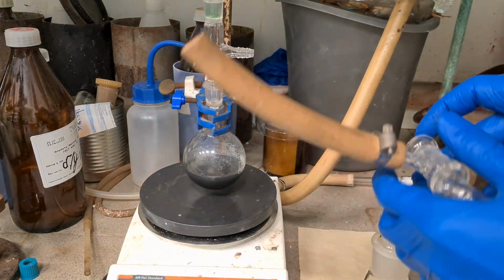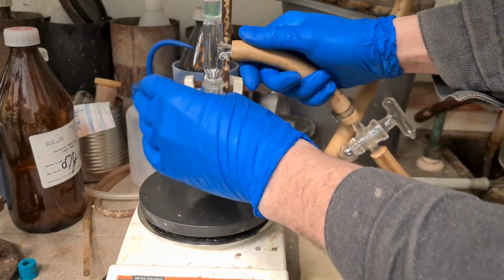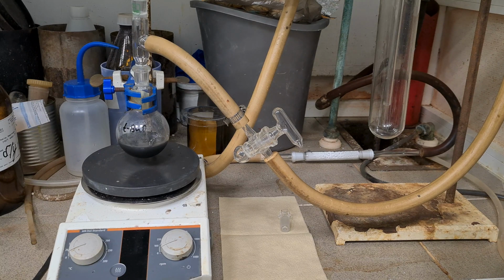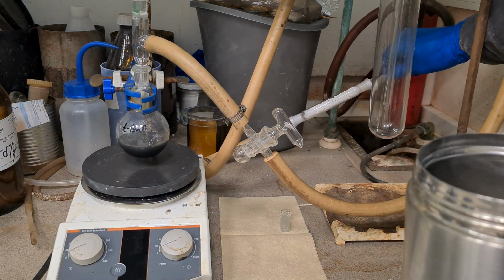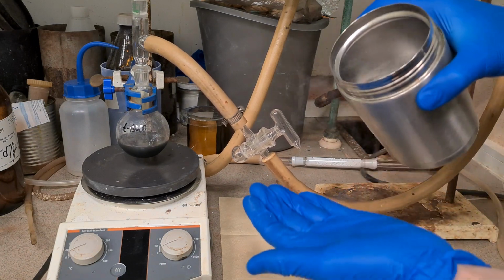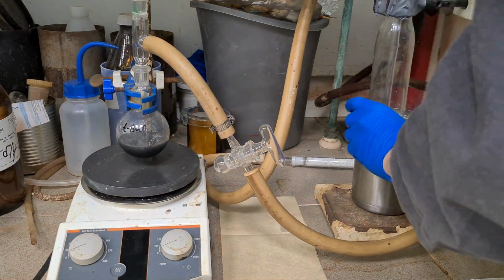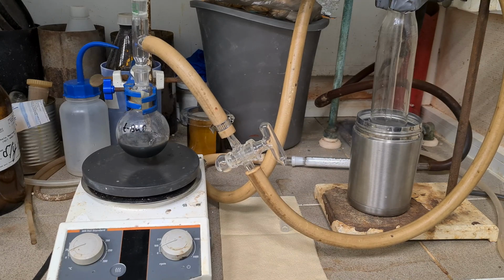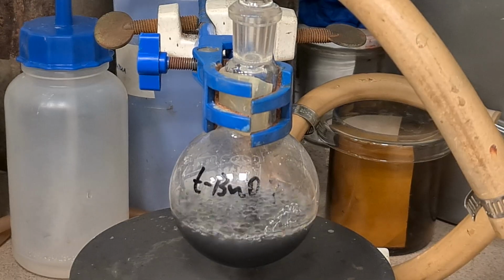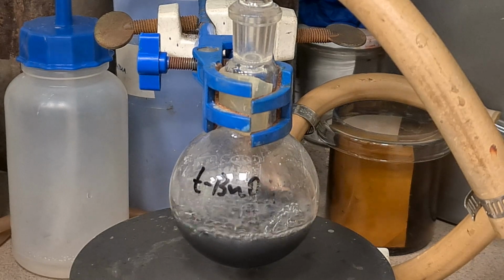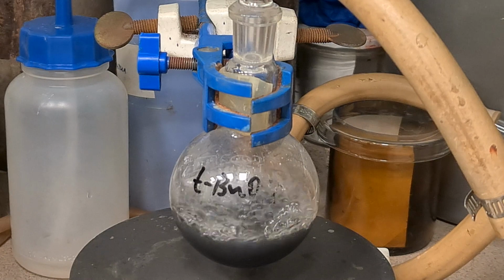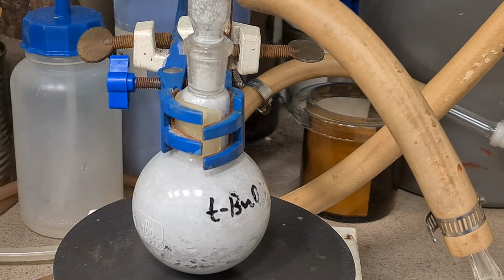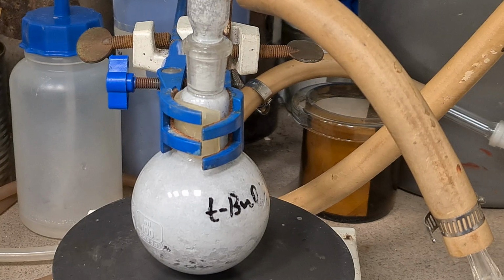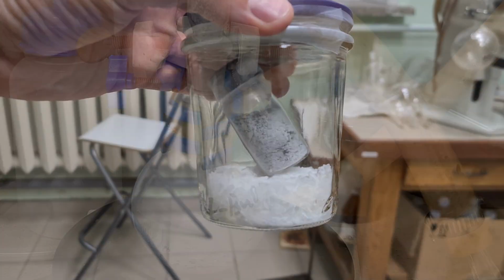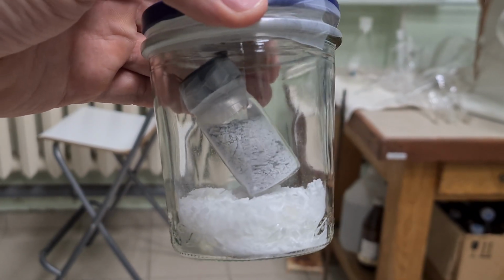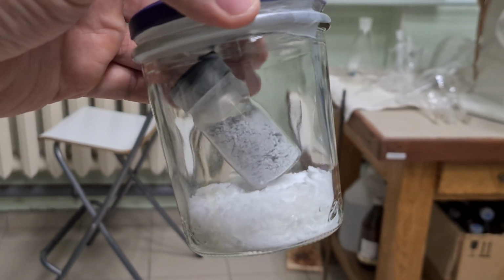I have used a water circulator pump connected to a liquid nitrogen trap, equipped with an anhydrous calcium chloride glass tube. As you can see, lithium tert-butoxide is just a white powder with a bit of gray shade. Finally, I have collected 6.75 grams of the final product, which corresponds to 83% yield.